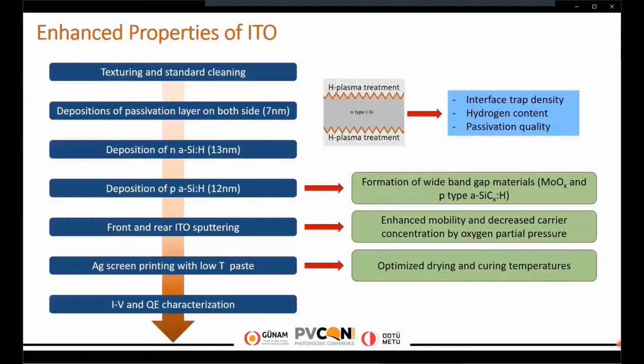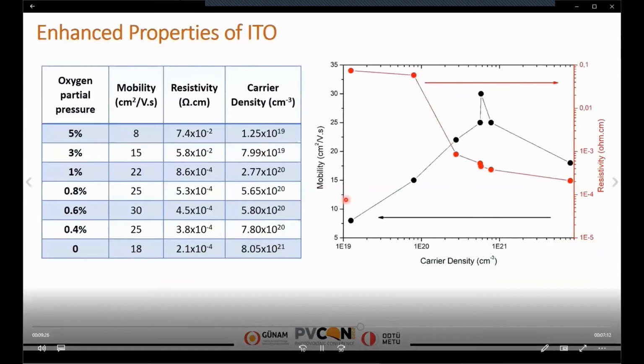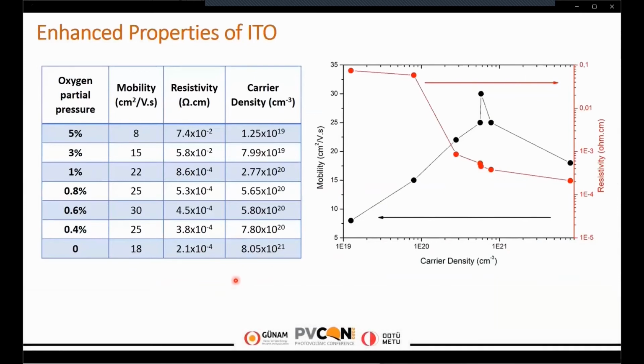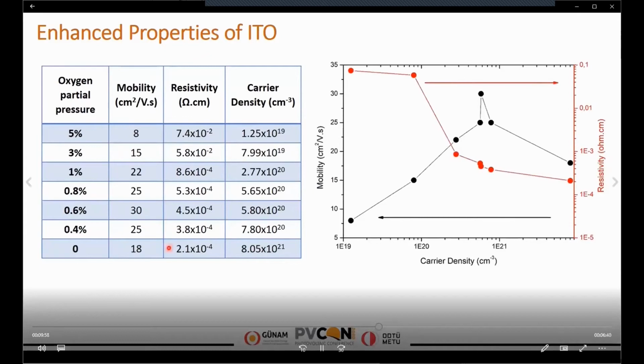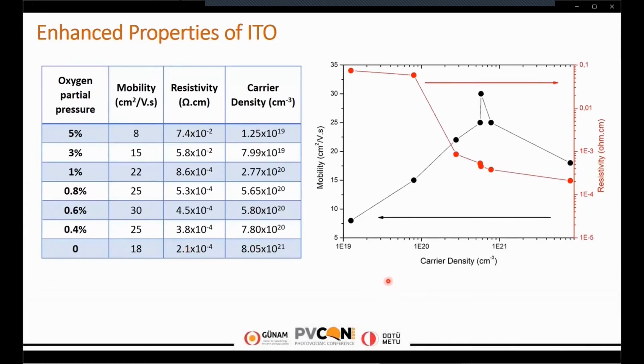Let's continue with enhanced properties of ITO by oxygen partial pressure. On the left-hand side, you can see the impact of the oxygen partial pressure on the electrical properties of the ITO layer. Increasing oxygen partial pressure leads to an increase in resistivity and a decrease in carrier density of the layer. However, for mobility, there is an optimum value at 0.6% oxygen partial pressure. Up to that value, the mobility increases, and after that it starts to decrease. And you can see the mobility and resistivity changes with respect to carrier density on the right-hand side.